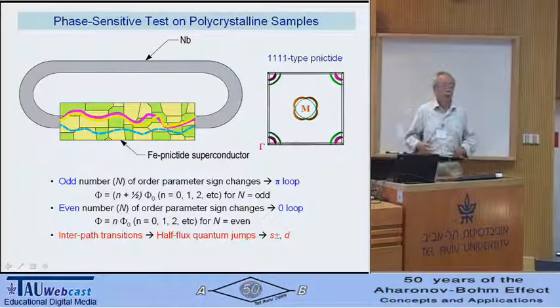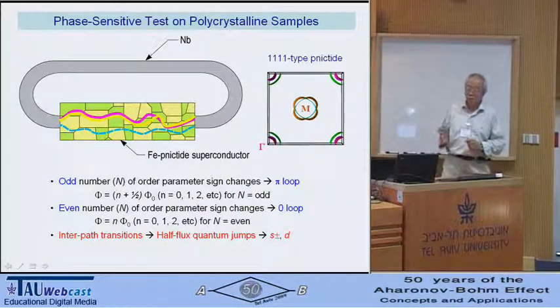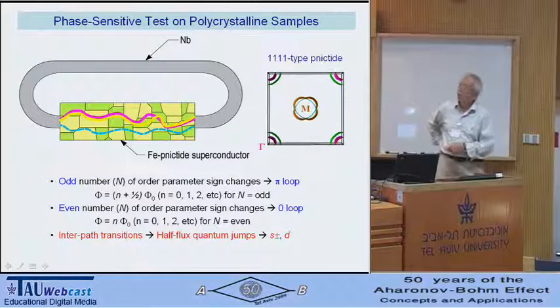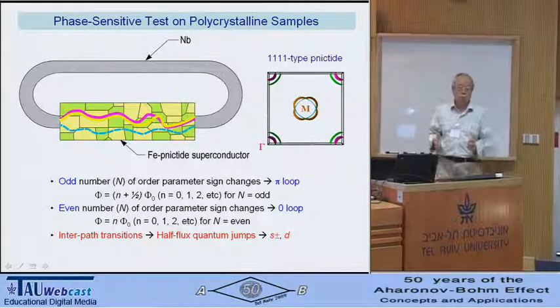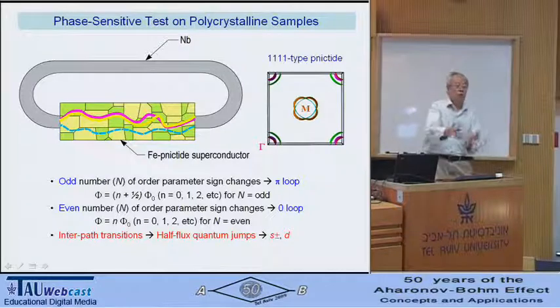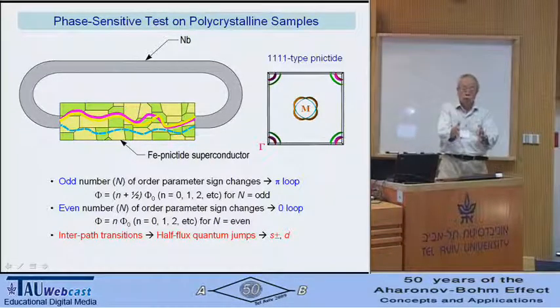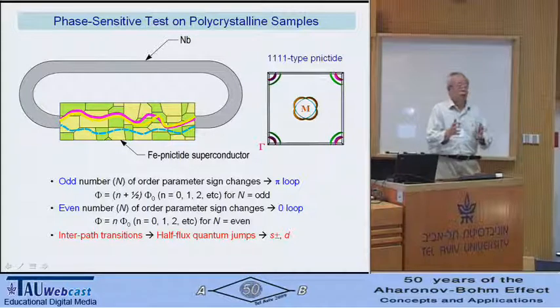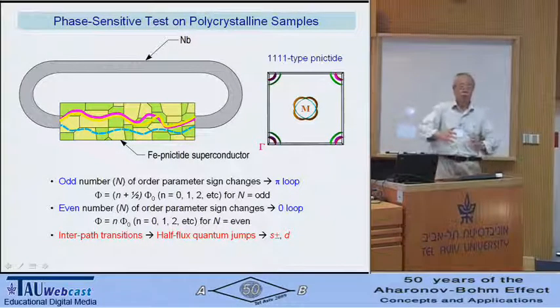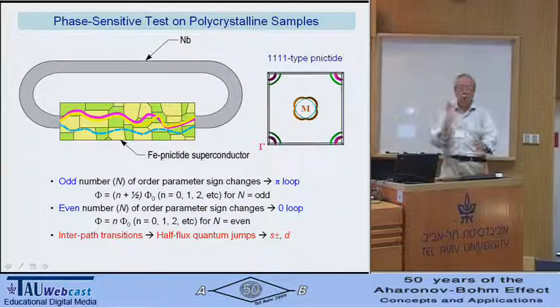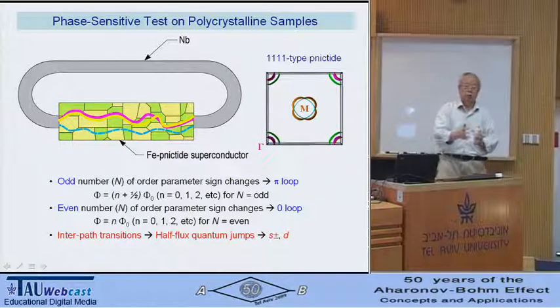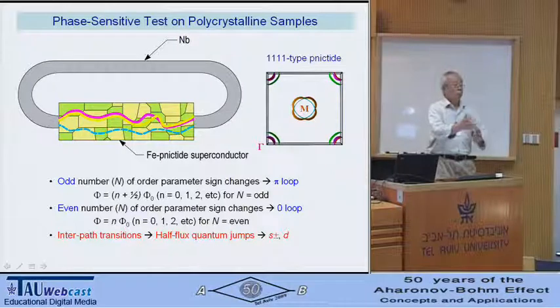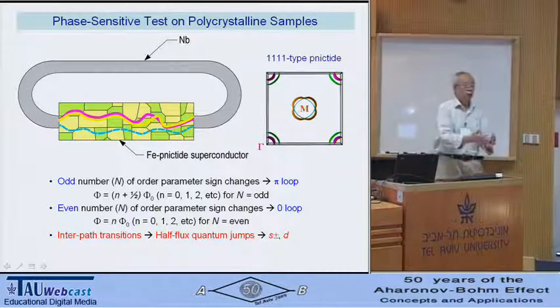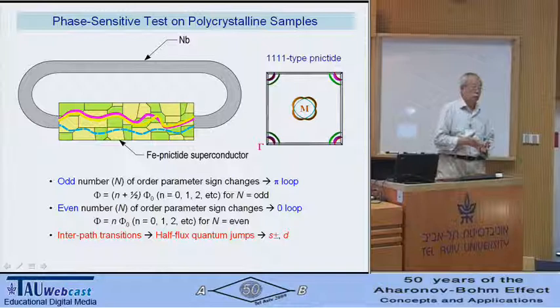Okay, now the next step is do the same experiment, but think about it. Since we use a polycrystalline material, you can have a different flow pattern of the supercurrent. And that supercurrent corresponds, in terms of the energy landscape, to different energies. So when you zap with the electromagnetic pulse, the main current flow will jump from one to another. One maybe contains no pi junction, the other one may have a pi junction along the way.